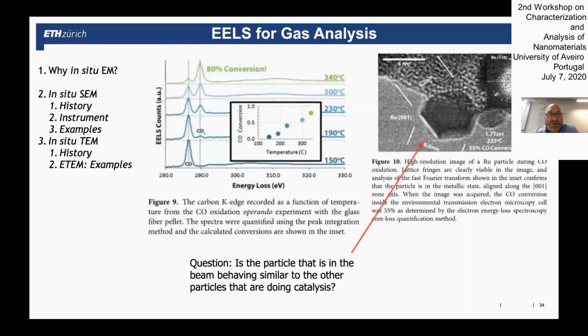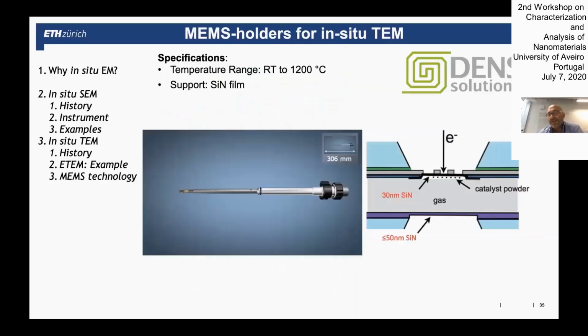The only problem that you always have in the microscope is you don't ever see all particles simultaneously. So some particles are in the beam, you illuminate them, the beam is hitting them, there is some interaction with the beam, and you never know: the particle that I'm looking at in the electron beam, is it really doing the same as all the other particles that are not exposed to the beam? And in the mass spectrometer, you actually have integral information. So this is actually a tricky point that we can discuss later if you like. And also this works nicely.